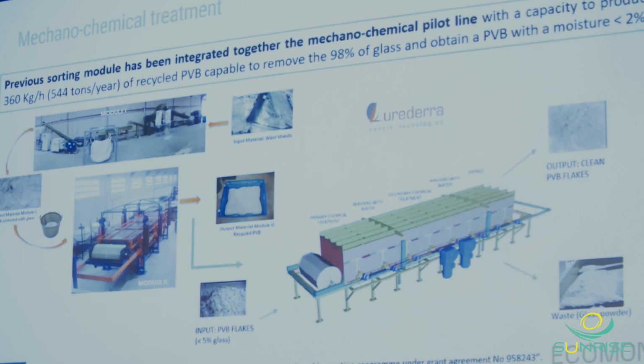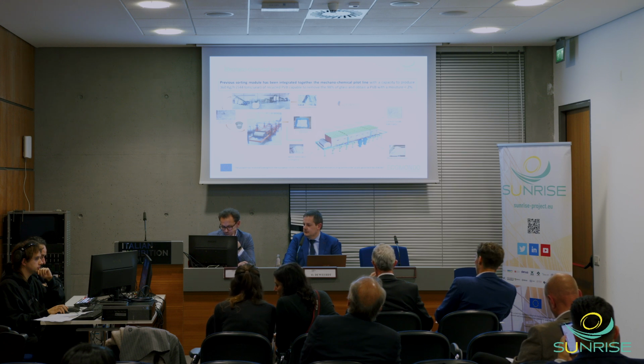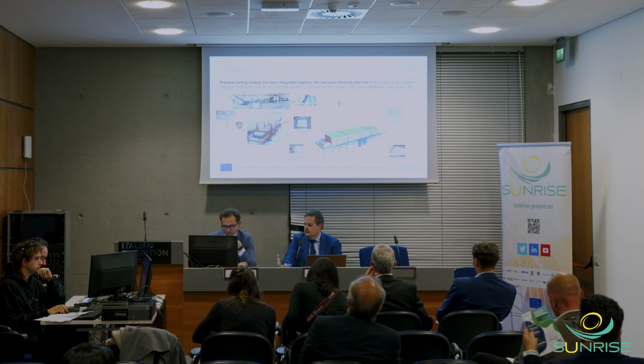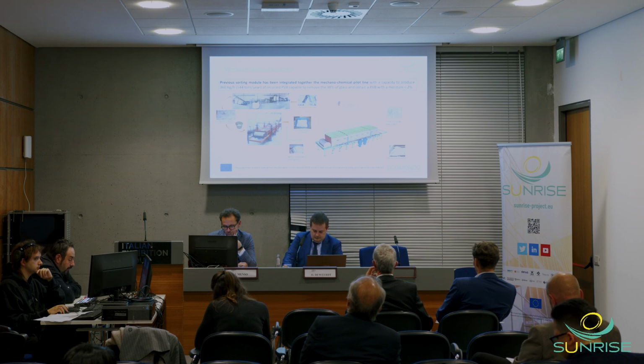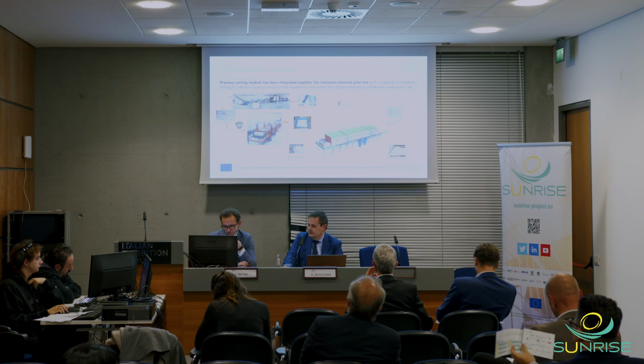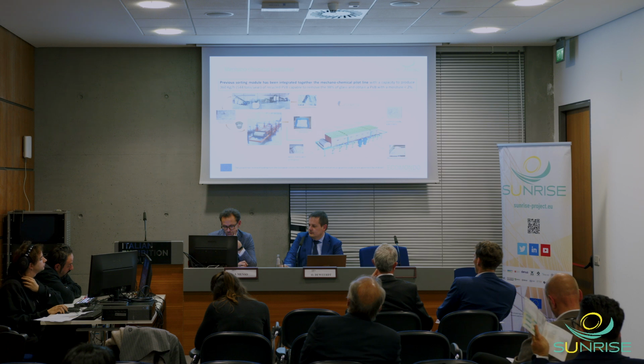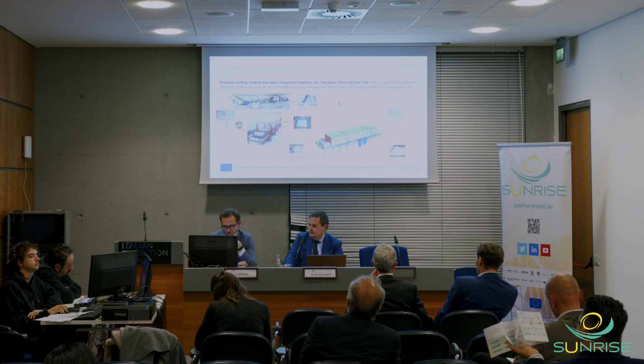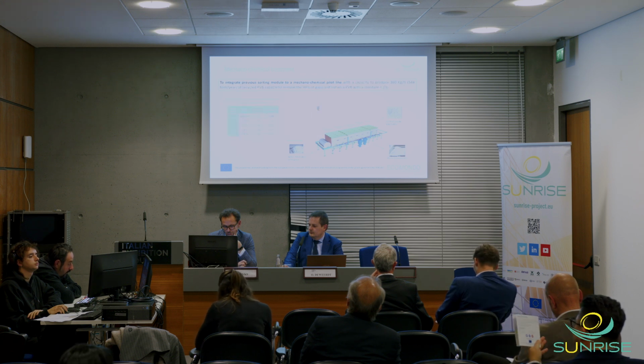Then this multi-sensor tool has been implemented in two different demo locations, one in Spain here in Lurederra, and one in Italy. In Lurederra has been included the full system, this multi-sensor tool that I showed in the previous slide. And this is installed in the location where we also have a mechanochemical pilot line for the purification of PVB from glass. So these are the images of the pilot line we have been using in the project for the posterior mechanochemical recycling. Basically what we do in this treatment is mechanically separate the glass from the PVB, and then with a chemical treatment in different washing steps, try to break the bonds between glass and PVB, to remove the glass from the PVB, sorry.